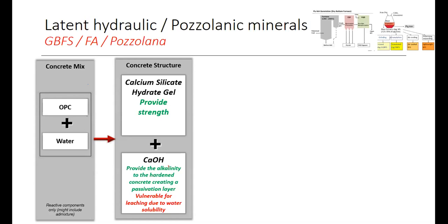The negative side is that calcium hydroxide has a good water solubility. So in case of moisture ingression into the concrete structures, the calcium hydroxide has a tendency to leach due to its high water solubility, creating a porous structure or an increase in the porosity inside the concrete. So there are both positives and negatives. If I blend the OPC with slag, fly ash or pozzolana, slag usually will not react with the calcium hydroxide. Slag itself has a chemical composition much similar to clinker, but it's very lazy. It doesn't have much reactivity.